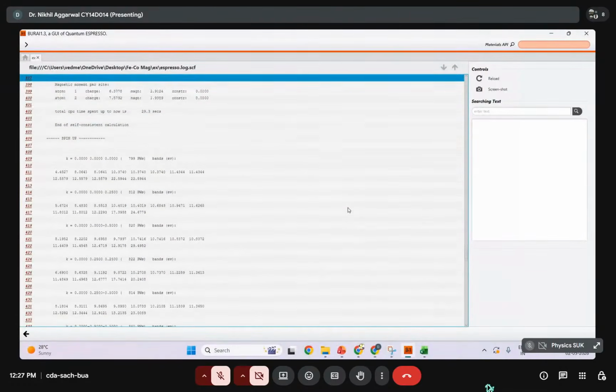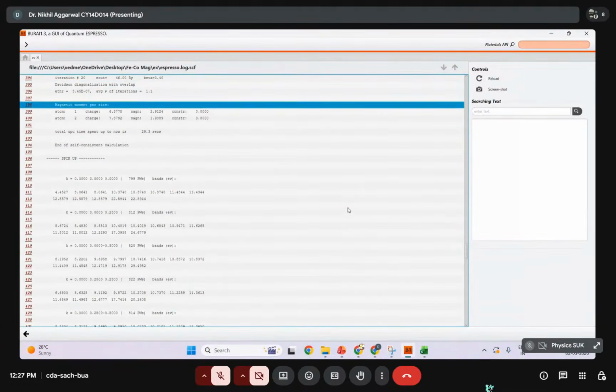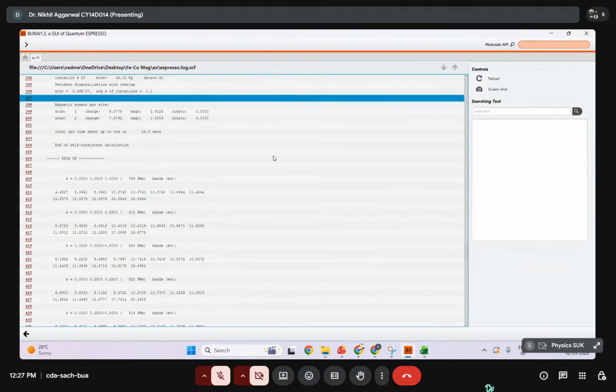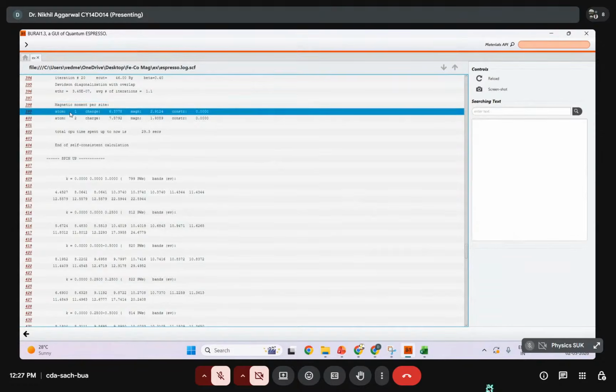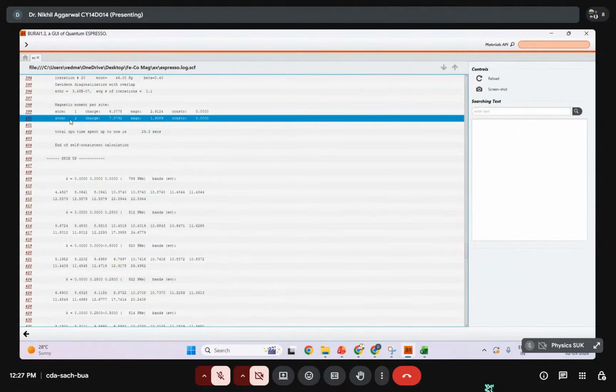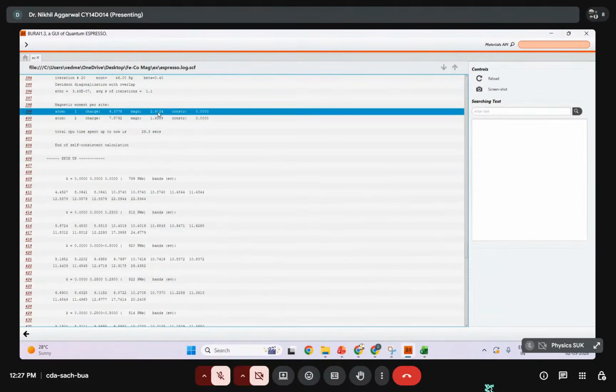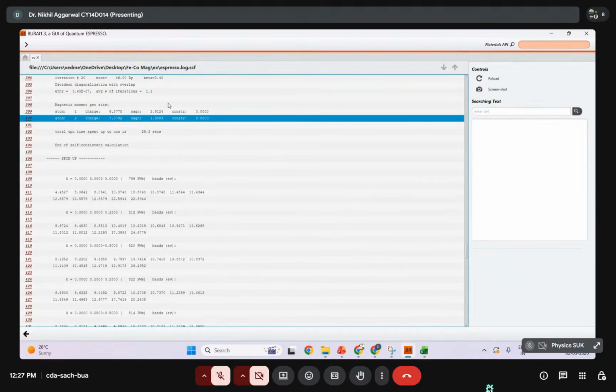The information corresponding to magnetic moment per site is there. The values will be written over here, magnetic moment per site: atom number one, atom number two. Atom number one, in our case, was the iron at the corner position. The software says it has a magnetic moment of 2.9, and atom number two has a magnetic moment of 1.9. So as the different types of atoms you have in the unit cell, in the lattice, you can study their individual magnetic moments also. And the total value you have already seen at the last, the 4.98 something.